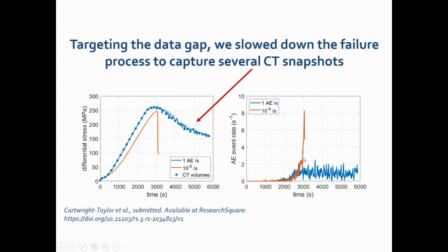So if you have no feedback control, you just see the inverse power law acceleration in event rate. If you do, then there's quite a bit of dither, which is quite standard actually in feedback control, hopping slightly back and forth, but it's feeding back on an event rate of about 1 event per second. And you can actually pick this up at Research Square, open source, at the moment while it's in review.